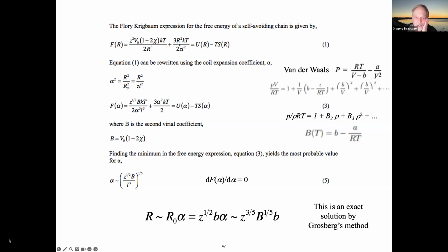So this has a temperature dependence. You have T's, and this one doesn't, even though it's got a T here, because chi is 1 over T, just like van der Waals' second virial coefficient is A over T. So even though you have T in both terms, this T gets canceled by chi, which has a 1 over T. So there's a hardcore excluded volume that's entropic, and this enthalpic excluded volume has to do with the attractive potential between the polymer and itself in the context of the solvent.